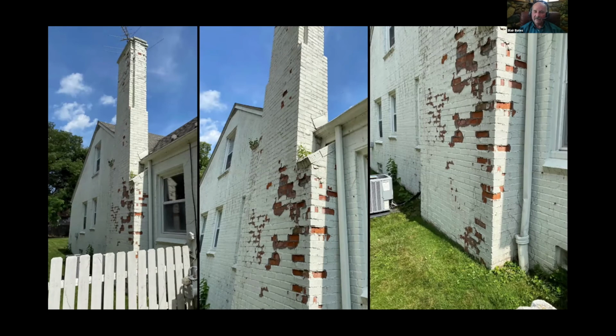If there's a lot of cracking, tuck point it. Don't use a painter's caulk and just go over it. You got to get the oils out of the caulk, so you have to let it fully cure. If not, you know, when you put the duct tape over your caulk tube to keep it from drying out, that oil will bleed right through your paint system.